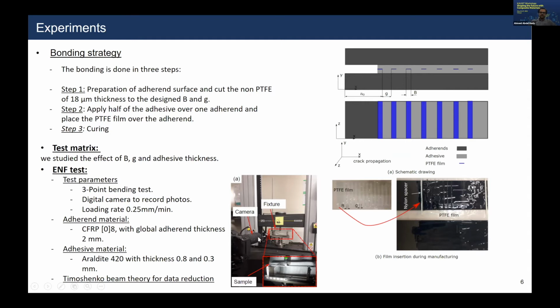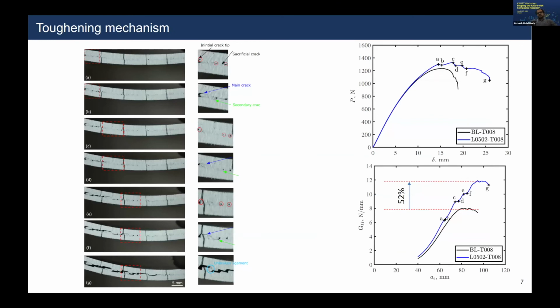We perform ENF tests to characterize mode 2 fracture toughness. In this work, a 3-point bending test was used, with a loading rate of 0.25 millimeter per minute. We used carbon fiber reinforced polymer adherend material, and the adhesive was a commercial one, Araldite 420, with two different thicknesses. Timoshenko beam theory was used as the data reduction method to compute the R-curve and the fracture toughness. I'll talk about the toughening mechanisms now.